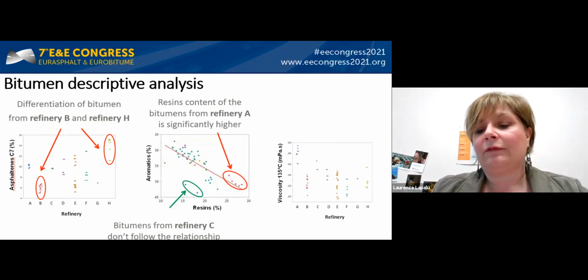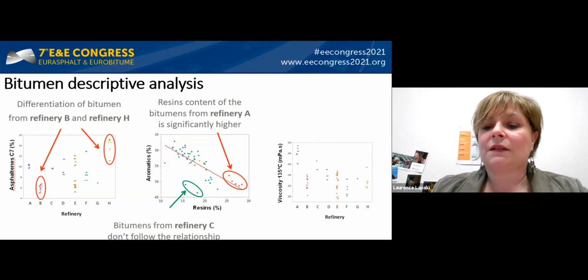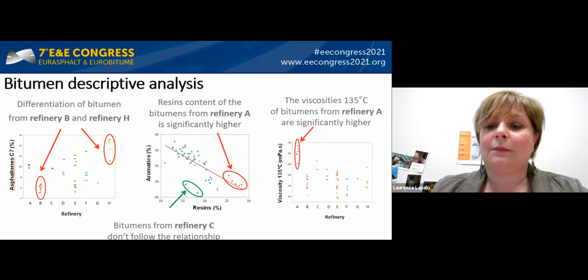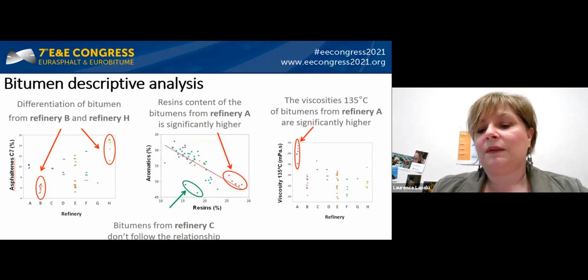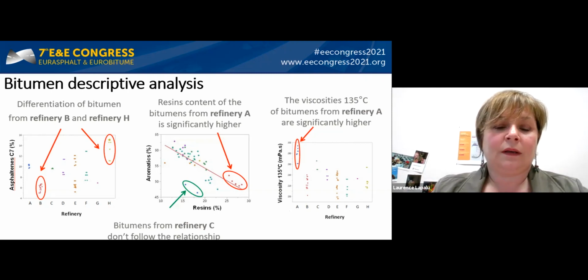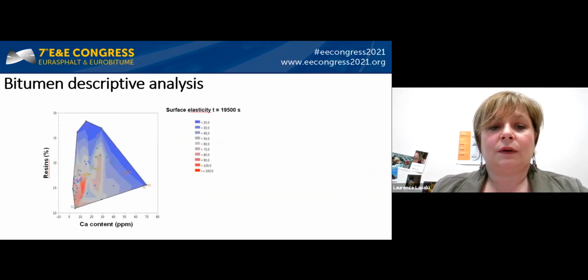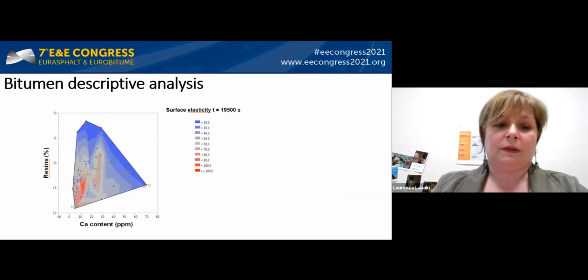If you look now at the graph on the right, it represents the viscosity at 135 degrees Celsius for the bitumens versus the refinery. And you can see that the bitumen coming from the refinery A displays high values of viscosity compared to the other bitumens. So this bitumen descriptive analysis shows that we have observed differences between the bitumens that we have taken into account in this study. We have also performed some interfacial measurements on the bitumens.